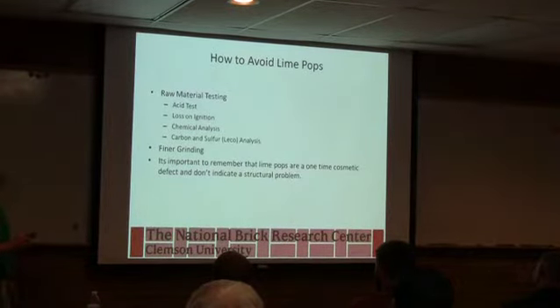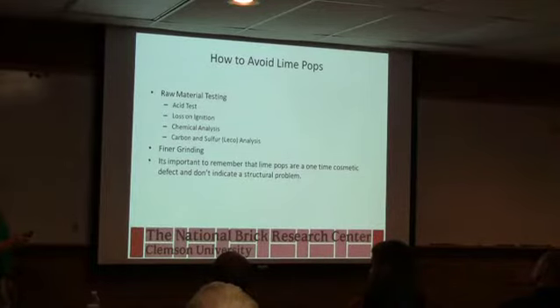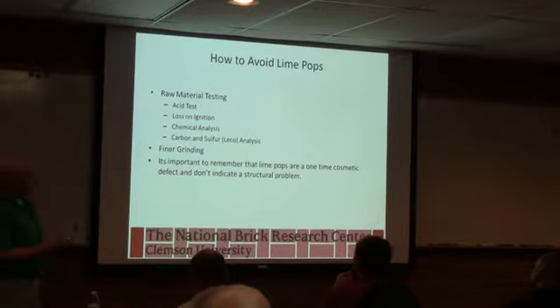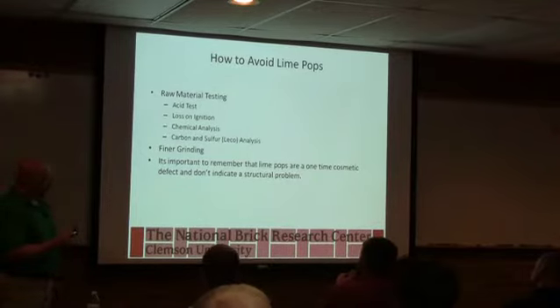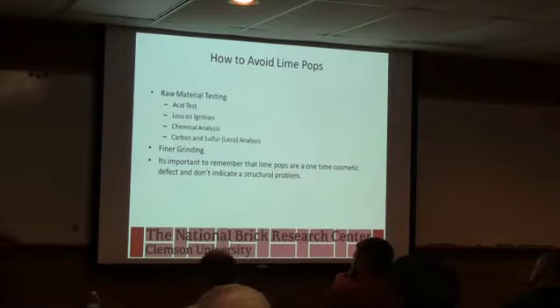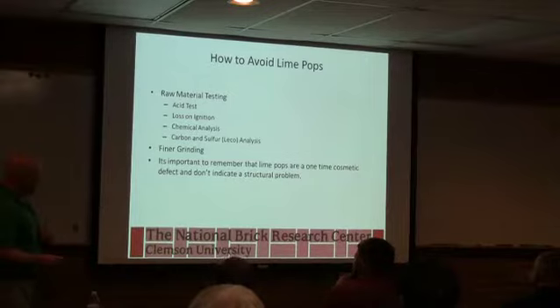So ways to avoid, one of the easy ways is you can look at your raw material, that acid test we talked about, but again, be careful with muriatic acid because it is pretty dangerous. Loss on ignition can be a clue like we've talked about, chemical analysis like we've talked about, and then that LECO, looking at how that carbon number changes. If you have a pure limestone, it's going to come up on the LECO at about 12% carbon. Usually for us, I don't know what you use as a red flag, but anything above 1% we start to get concerned about when we're doing analysis.